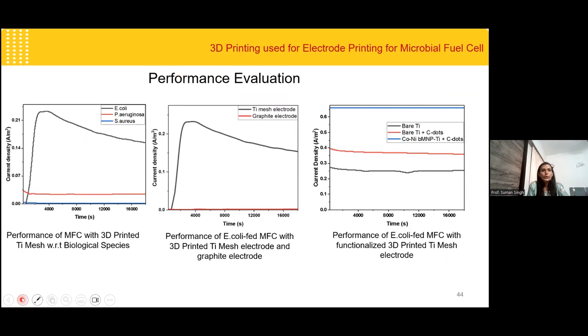This is the performance evaluation of our electrodes, and first one is with the different biological species which can be used for microbial fuel cell applications. From here, we could see that E. coli was a better species which gave the required response. Then we compared the response with the titanium mesh electrode and the graphite electrode. The graphite electrode was normal, and this mesh electrode was 3D printed from titanium. It showed enhanced performance as compared to the graphite electrode. That's why, after optimizing the species and then the electrode material,